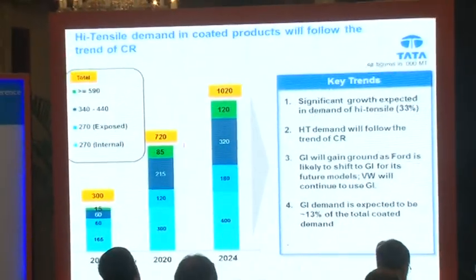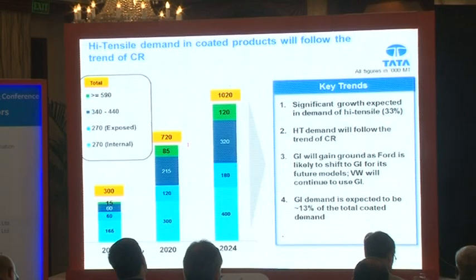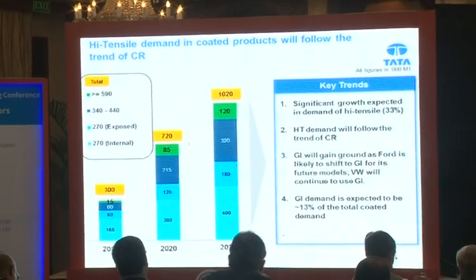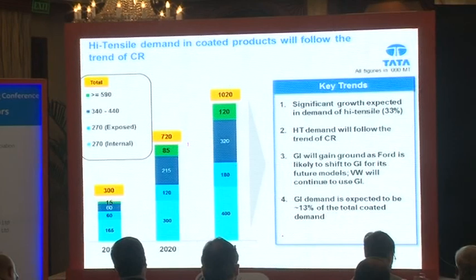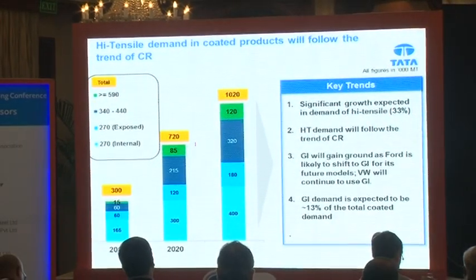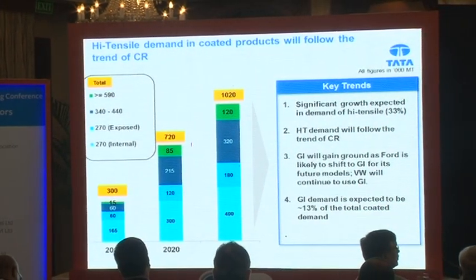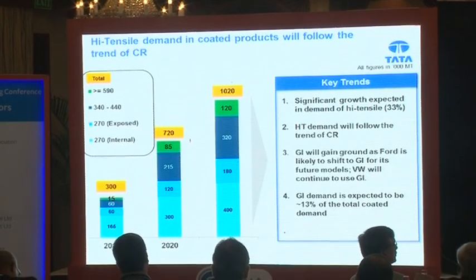So the automakers want to shift now to coated steels for corrosion resistance, but also want high tensile coated steels. Now that presents another big challenge, because producing high strength coated steels is more challenging than producing cold rolled high strength steels. So what we see here is that yes, the demand for coated steels will rise, and this graph is our own team analysis. Also, there will be a lot of usage of high tensile coated steels.